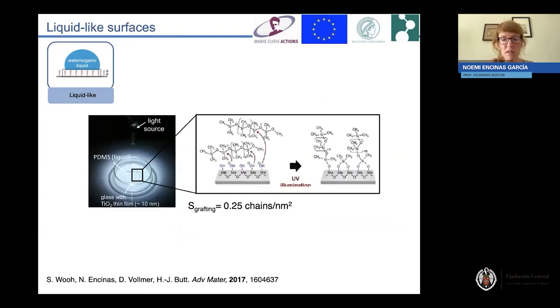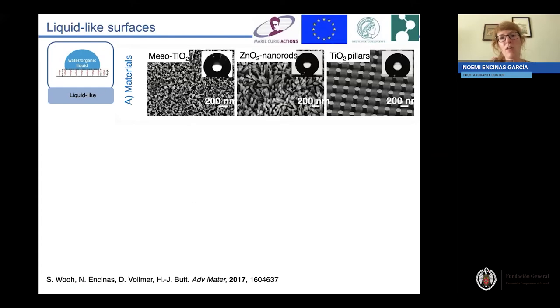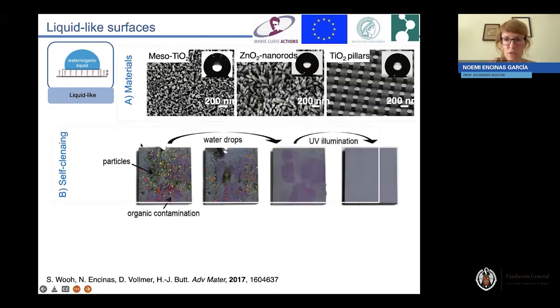So the methodology was quite simple. We just had a cover glass coated with a titanium dioxide thin film, and we immersed it in a PDMS liquid. Upon irradiation with UV light, we were capable of covalently grafting PDMS brushes, which were acting as a liquid-like surface. And firstly, we saw that this type of coating could be applied to very, very different types of surfaces, which could be almost universal, let's say. It presented really good self-cleaning